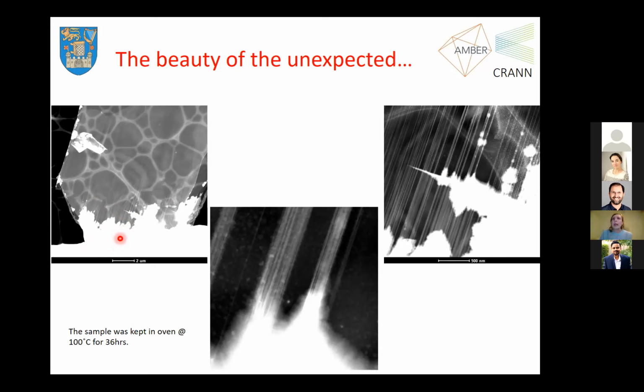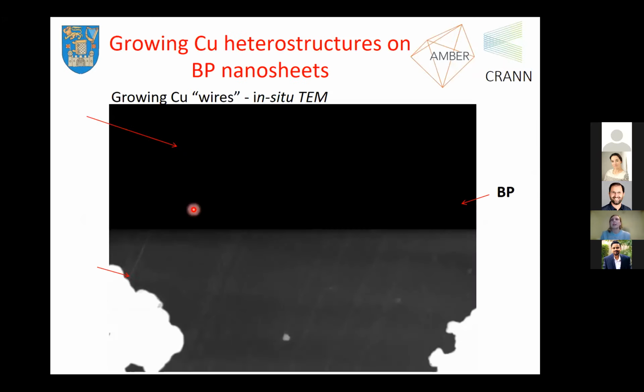And what we realized when we put the sample back in the microscope was these very odd and strange lines building up. They were always parallel to each other, and always starting from the edge of the copper grid. At that stage, we were very horrified. We didn't know what this was. We thought it was just something wrong with the sample. We prepared a huge amount of different samples, again with the same procedure, and every time this happened.